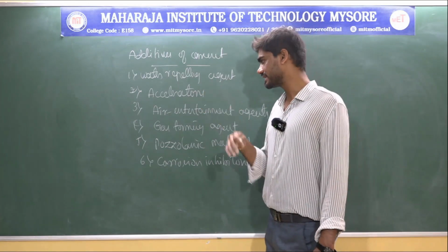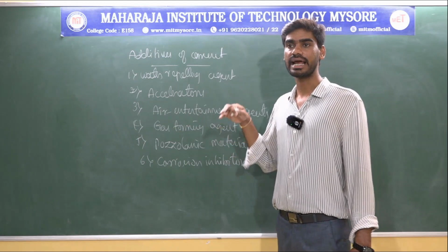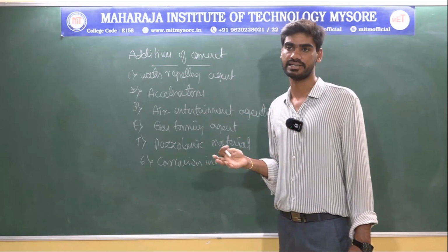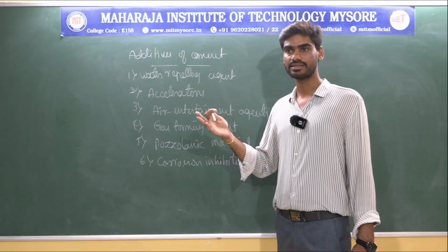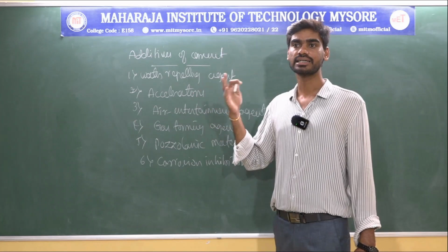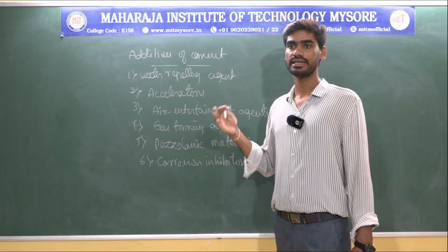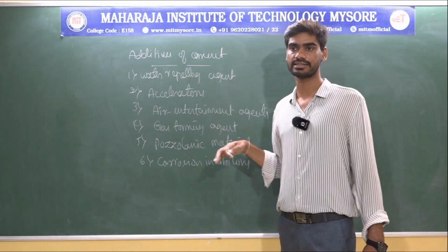When it comes to the accelerator, the name itself indicates that these additives are added to increase the early strengthening. Chemical compounds such as common salt like calcium chloride, organic compounds like triethanolamine, and other soluble compounds like carbonates, silicates and fluorosilicates are commonly used as accelerators.